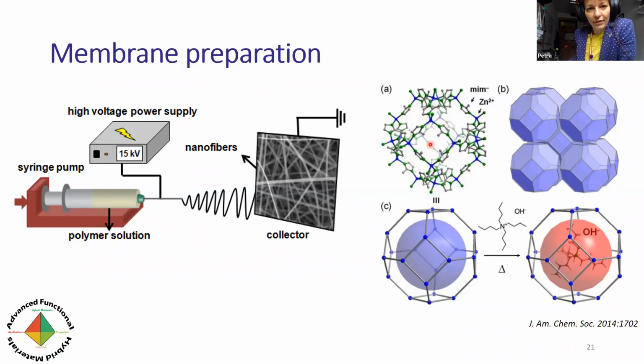Now this is obviously a charge neutral framework, and to make it intrinsically hydroxide ion conducting, what they did is graft an ionic liquid on it whose anions were hydroxide ions. So the cation is the tetrabutylammonium ion, which can form hydrophobic interactions with the methyl group here. And as you manage to graft the cation on the framework, essentially making the framework positively charged if you wish, you can bring the hydroxide ions into the pores, which are ideally loosely bonded mobile ions, which will in turn endow the framework with hydroxide ion conductivity. I should say that they did improve the conductivity, but still it was relatively low. But we thought it was a good model system for us with which we can work and see if we can make a processed membrane out of it.